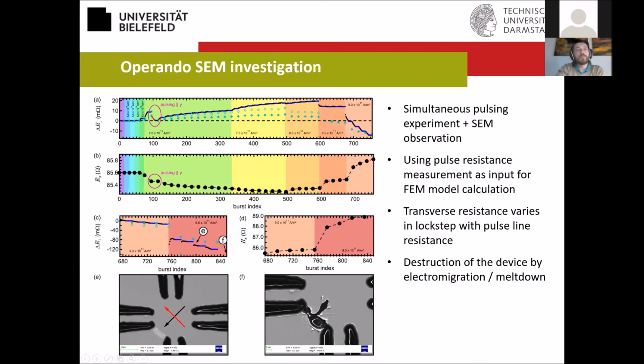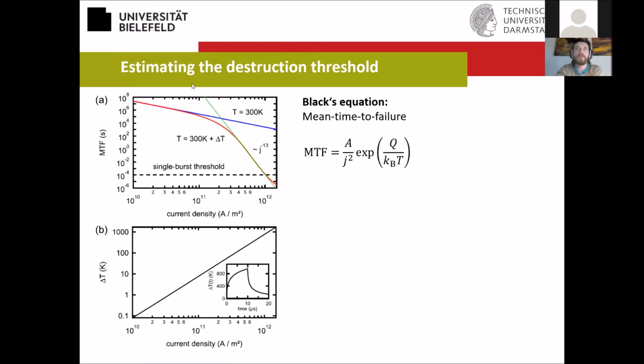And in the end, as we break the device, we see just before it breaks that something happens here in this narrow, and finally our device melts in this spot. So this is what the destroyed device looks like. This gives us an indication that this destruction is due to electromigration just before the meltdown. Now we can estimate the destruction threshold through Black's equation for the mean time to failure due to electromigration.